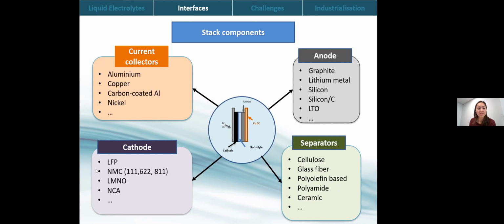And also on the cathode side, there can be dissolution of metals into the electrolytes. A lot of factors can affect this. So interfaces need to be studied for each pair of electrode and electrolyte. We have LFP, and we have also studied extensively NMC 111, 622, 811, LMNO, and NCA. All of these have different reactivity to different electrolytes and additives. So there are a lot of things to consider.